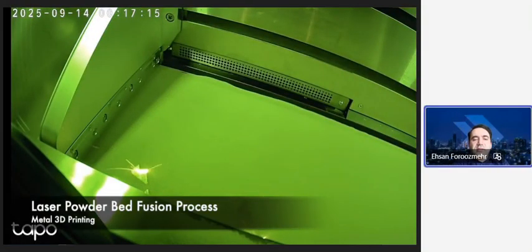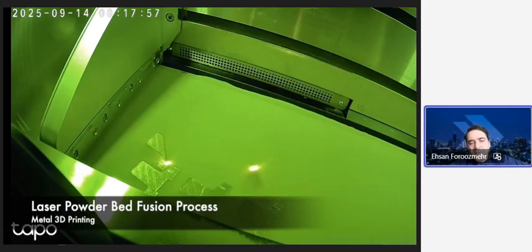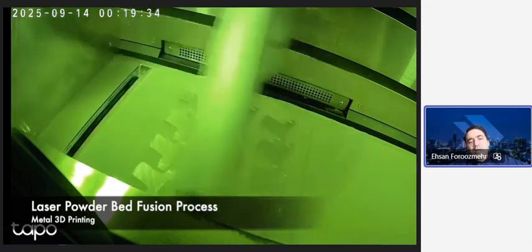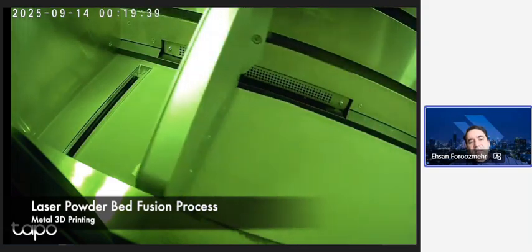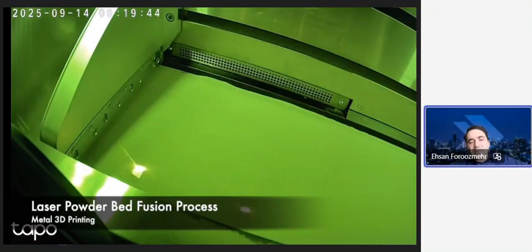Then the machine starts by taking the information from the software and sending it through the laser system and scanning system to precisely find where the laser has to move and melt the part. And as you can see, with a very thin layer of powder, you actually don't see the previous layer because the layer is about 60 micron here. Once the process is over, you'll see the next layer come over and you won't see the previous layer anymore. Wherever is melted is the part, and wherever is not melted stays as a powder, and the powder will be reused in the next process.